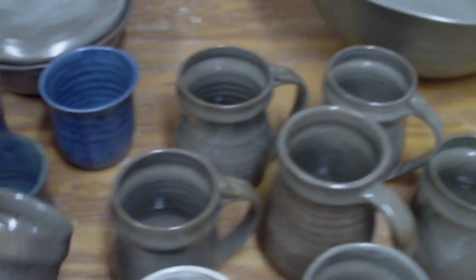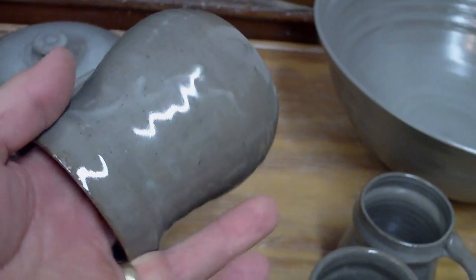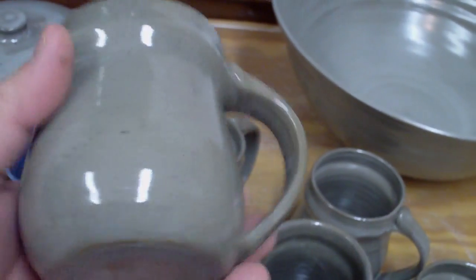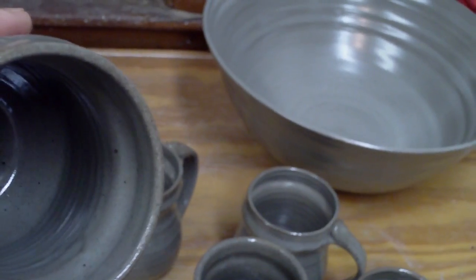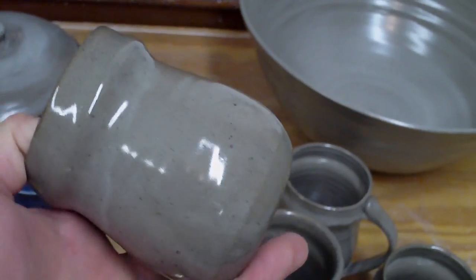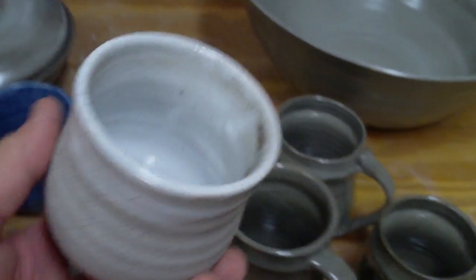Unevenness, drips — this one here drips, I cannot get this to glaze evenly. I'll take advice from anybody. This one didn't come out too bad — look, dripping there again. I think if it fired correctly, see how the celadon is kind of greenish milky — if it fired correctly it would be more clear green and you wouldn't see those drips as much.